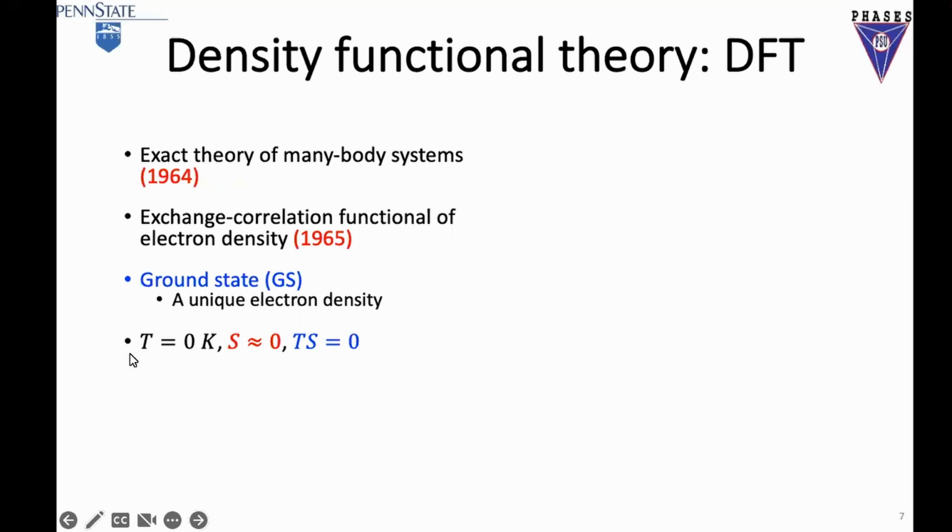But now if you increase the temperature for that ground state, we know there are at least two contributions. The first one is the electronic contribution, you have a distribution of electrons, and you have the vibrational contribution. Together that is larger than 0. Okay, and then TS is larger than 0. That means it's no longer a pure quantum state, so not a ground state. If the ground state is not a pure quantum state, that means we cannot use the particular statistical mechanics from before anymore, right? But people still use it. You look at today's publications, everybody uses the same equation for non-pure quantum states.